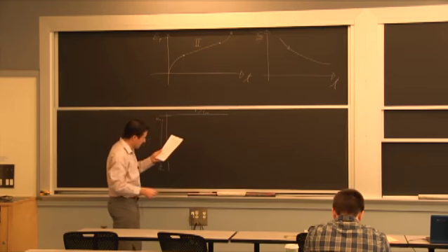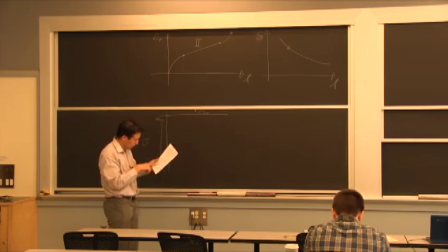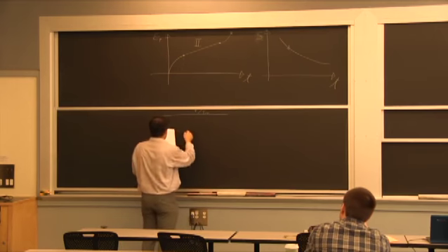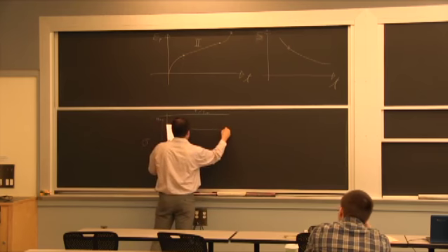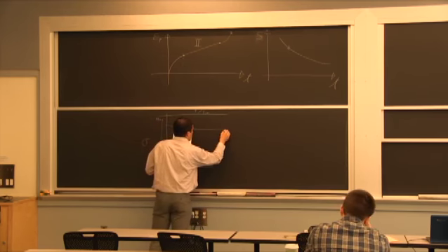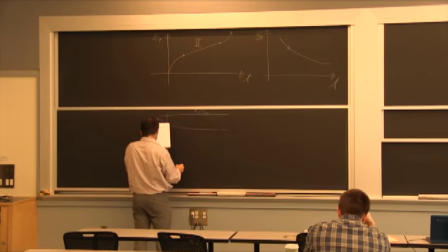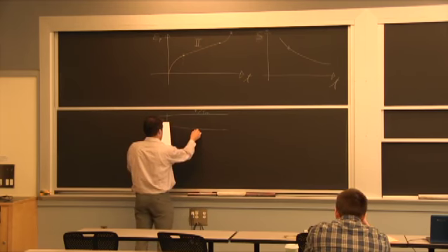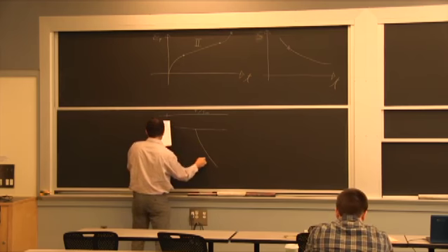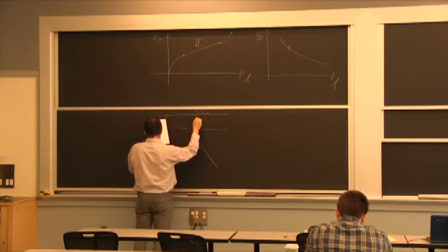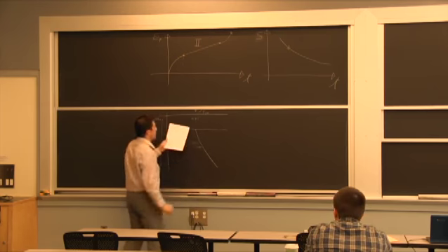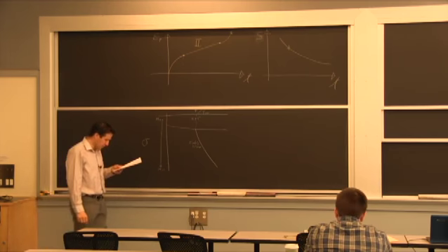You can see from this plot the first curve that comes for what we call Coble creep. So it looks a little bit like this, where you have more or less the uniaxial loading response. This is rapid loading. When you see this first intersection here for Coble creep, you are already here at about 0.35 of the melting point. What does that mean?